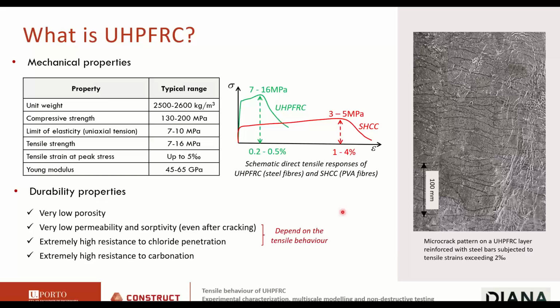So the mechanical properties are really distinguishing. So this material really stands out from conventional concrete. So the unit weight, it's not much heavier than standard concrete. The compressive strength in typical compositions can vary between 130 to 200 megapascals without heat curing. If we have heat curing procedures, we can get higher values sometimes.